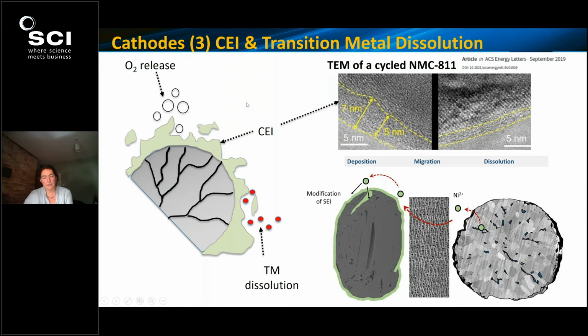So a lot of studies have been carried out on manganese, but as we're trying to develop more high nickel materials, which contain, so for example, the NMC 811 material contains 8 times stoichiometrically more nickel than the other transition metals. And so there is the likelihood that more of this will then enter the electrolyte, find its way through the separator onto the anode. And this is a very interesting current research area to know what effect this can have on performance.